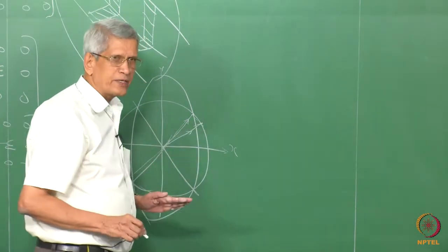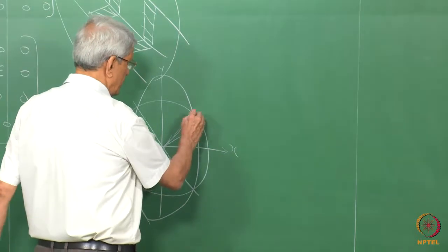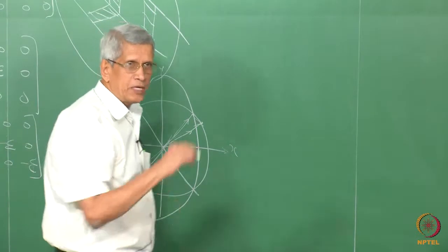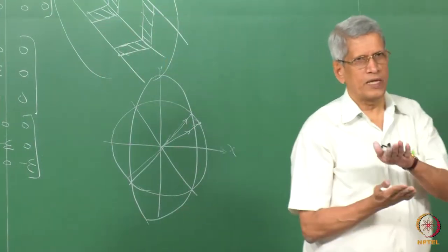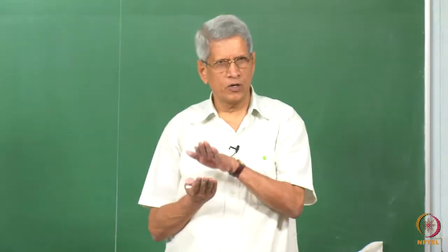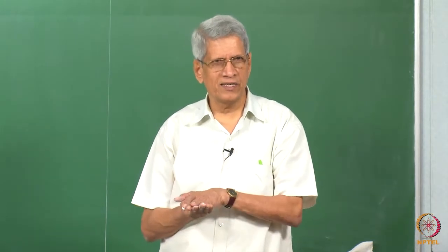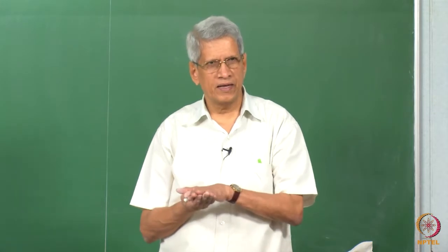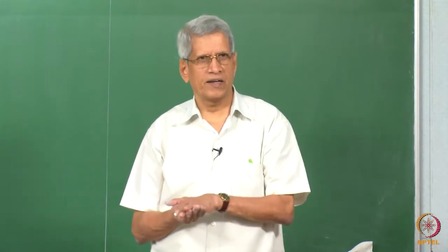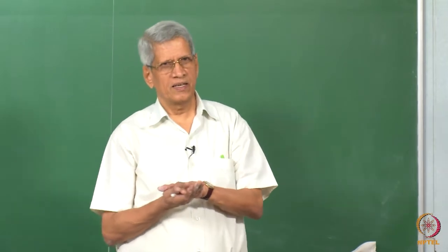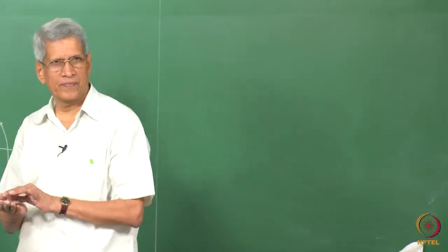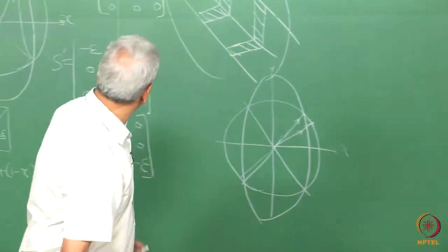And this is the original plane in which this vector was lying. This corresponds to a matrix. That means that if we try to rotate it back from here to here, we will be able to generate the two planes which are matching with each other. That means an unrotated and undistorted plane could be generated. That plane is the habit plane of the martensite, or we call it the invariant plane, right, the lattice invariant plane. Okay.